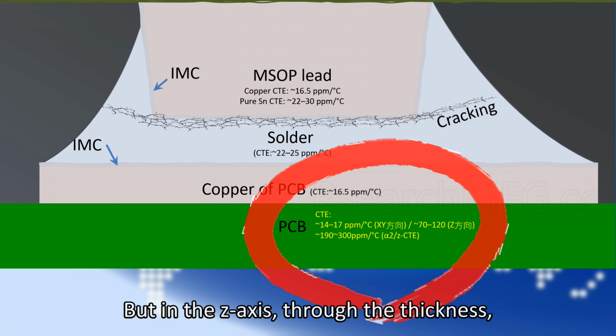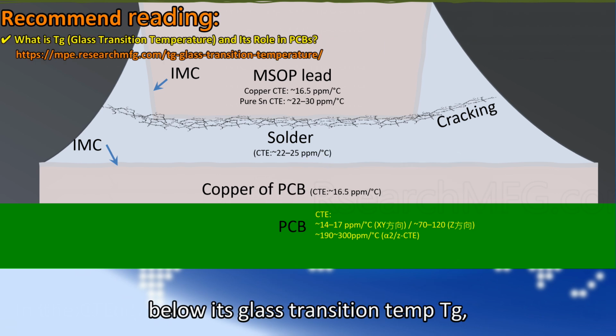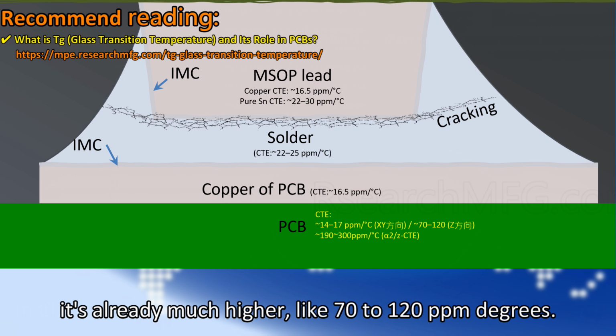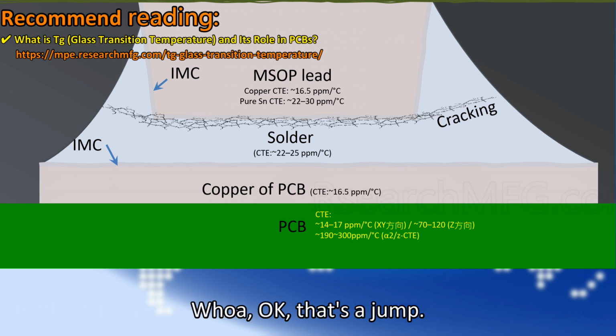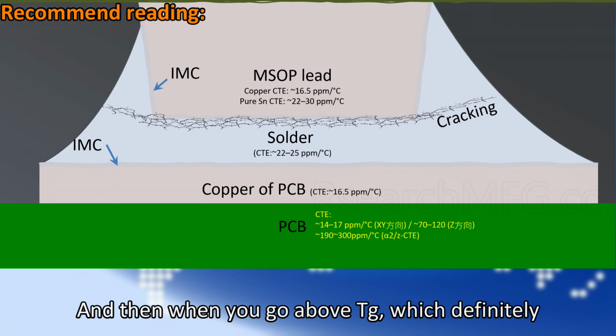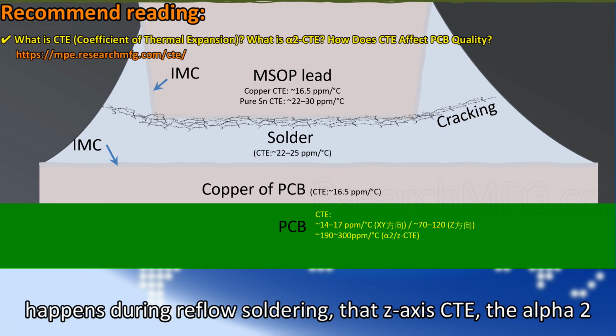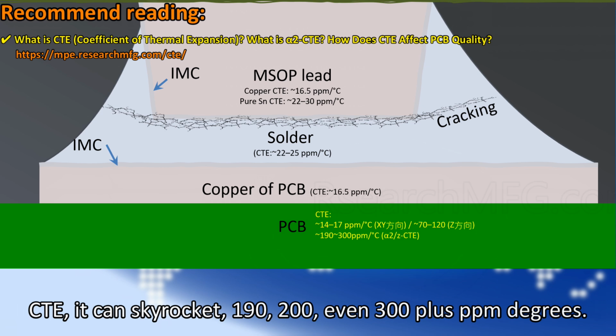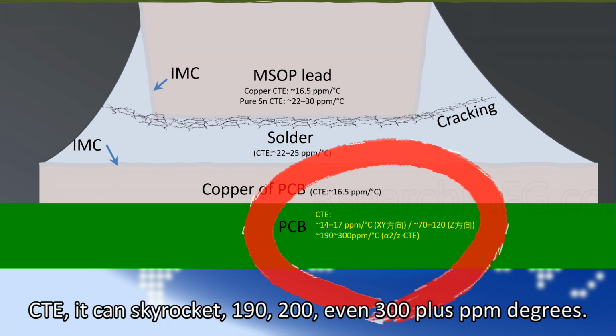But in the Z-axis, through the thickness, below its glass transition temp, Tg, it's already much higher, like 70 to 120 ppm per degree. Whoa, okay, that's a jump. And then when you go above Tg, which definitely happens during reflow soldering, that Z-axis CTE, the alpha 2 CTE, it can skyrocket to 190, 200, even 300-plus ppm per degree.